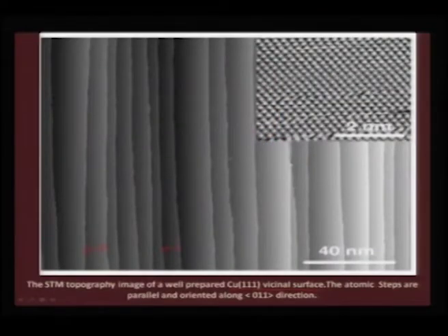The same material, suppose I want to grow iron film on copper 111, the terrace and the morphology of your copper 111 surface will initiate a very different growth process compared to a copper 100 growth process. So, if you want to understand in atomic scale how this growth process proceeds, then you need a very good understanding of the STM. So, STM plays a very important role therefore to dictate the growth mode,